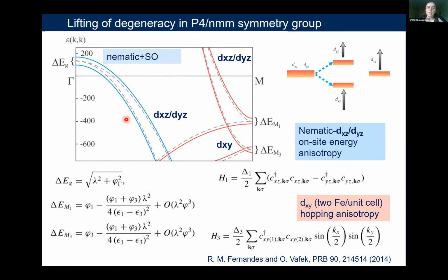So to further understand the difference between the hole bands and electron bands, this is a very good representation of those effects. So as I said before, as you break the symmetry from this tetragonal symmetry where you have the general dxz and dyz state, these two bands will shift, and then we also have a dxy band very present in many of these pockets, in particular for the electron pockets. So we expect that for the gamma band, as I discussed before, we already have an effect to do with spin-orbit coupling, which is about 15 millielectron volts. But as we turn on the nematicity, this band will shift.